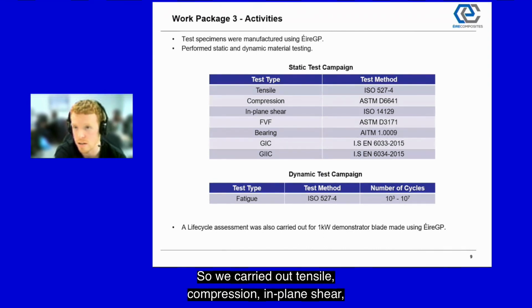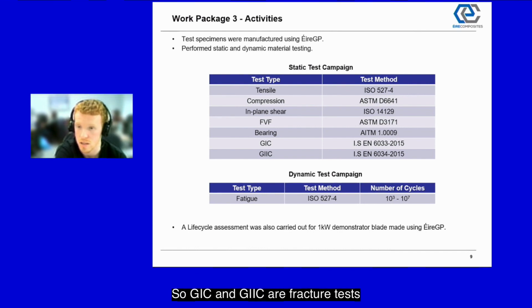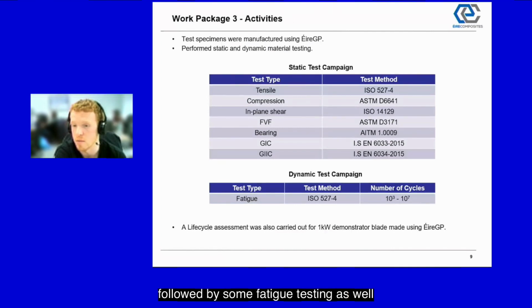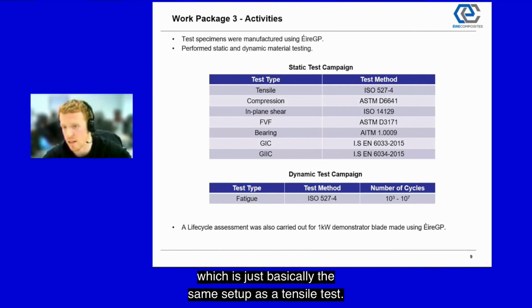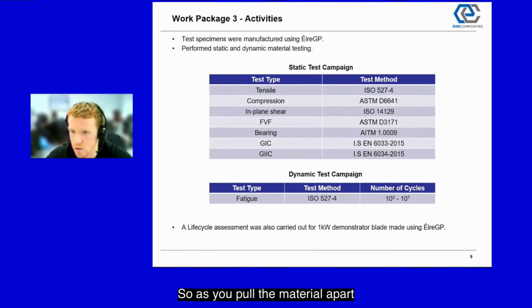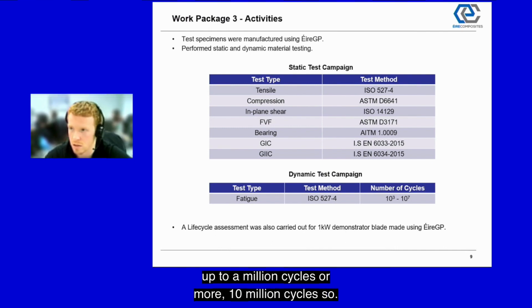We carried out tensile, compression, in-plane shear, fiber volume fraction, bearing load, and fracture toughness tests. So G1C and G2C are fracture tests, followed by some fatigue testing as well, which is basically the same setup as a tensile test. As you pull the material apart, you cycle it from 1,000 cycles up to 1 million cycles or more, even 10 million cycles.